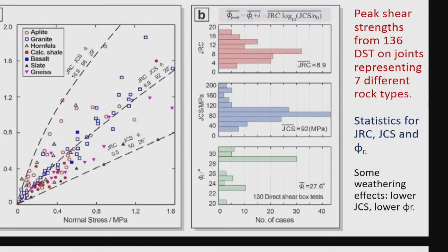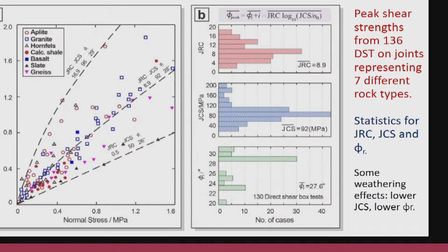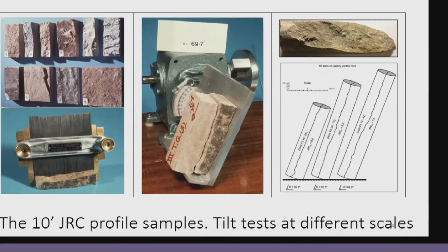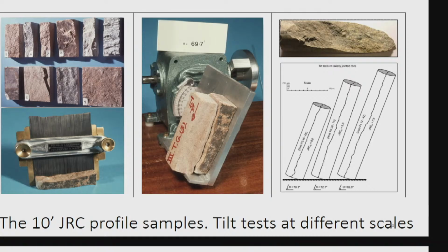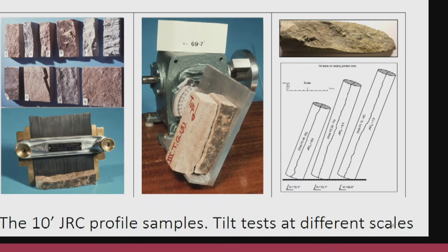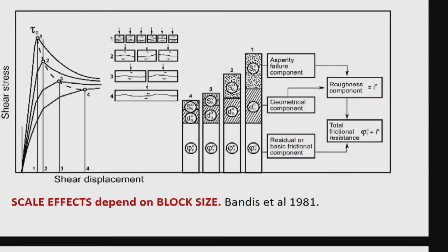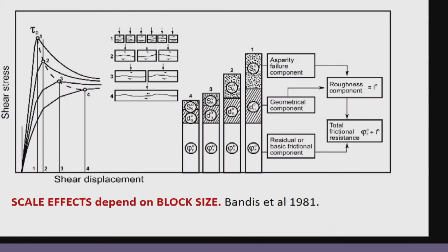Those are the shear tests that we did a long time ago at NGI to get the range of JRC and JCS for 7 different rock types. And there's no cohesion. If you look down at the axis, there's no actual cohesive strength. And we did the tilt tests. Those 10 samples are actually the origin of the 10 roughness profiles that were just shown. And thanks to Bandis, there was the concentration on the effect of block size.